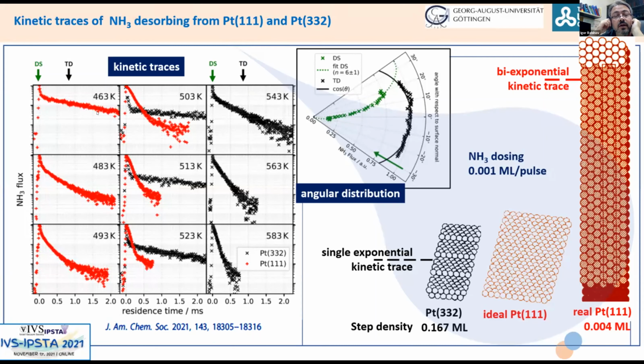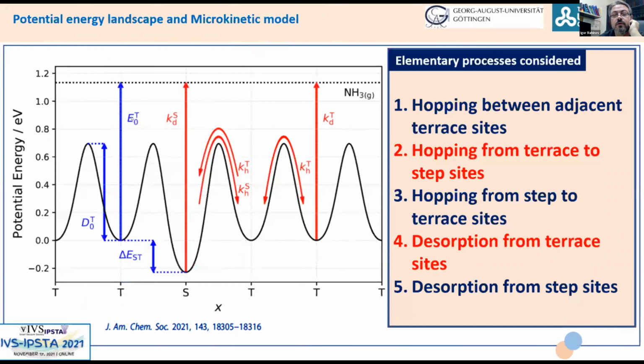We see that in the case of platinum-111, the desorption trace is bi-exponential, while in the case of platinum-332, the decay is single exponential, okay? So this is what the time-resolved kinetic trace, time-resolved desorption, tells us. So we can try to model this with a fairly straightforward kinetic model, considering the following elementary processes.